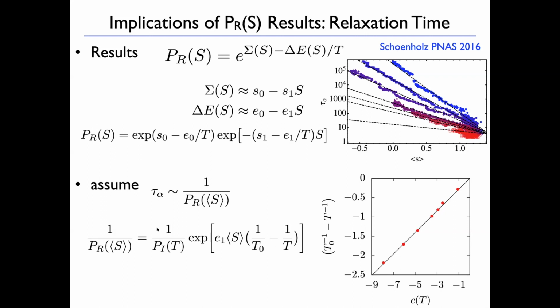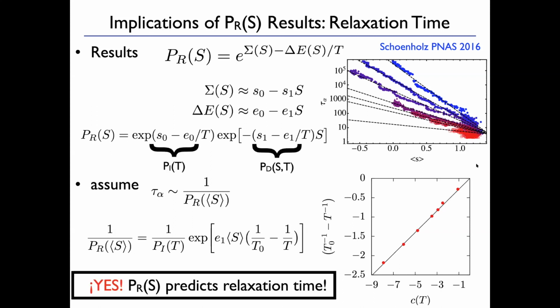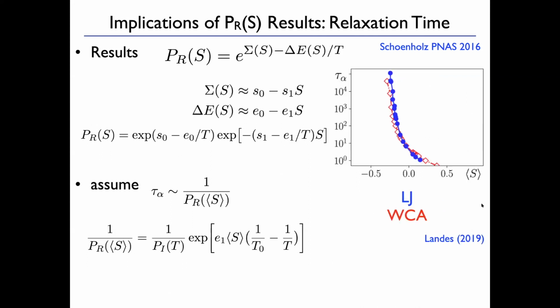So that says that the log of the relaxation time should be linear in the softness, with a slope which is 1 over the onset temperature minus 1 over the temperature that I quench to. And that's what I've plotted here. This is the actual slope that I got from these curves, and it works beautifully. So what that says is that indeed, I can get the relaxation time from the probability of rearranging softness.